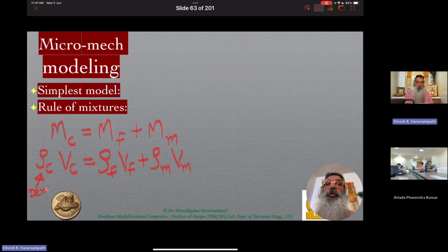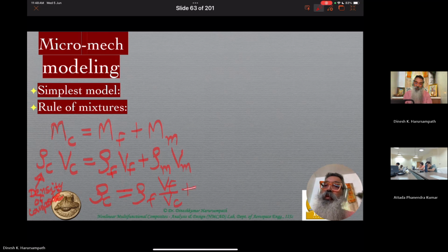So if you want to get to the density of the composite as a function of the densities of the constituents, which is the fiber and the matrix, then you see that it's quite simple: all I have to do is bring VC to the other side. So I will have my rho C, which is the density of the composite, equal to rho F times VF divided by VC plus rho M into VM divided by VC.